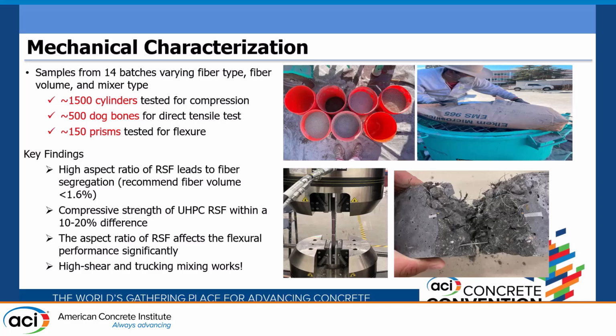So again, it's an optimization thing. If you use high aspect ratio, you're going to have a lot of fiber segregation issues, but you still want to have that flexural strength, so that's why you have to meet halfway. Also, we saw that a high shear mixer works for recycled fiber, but for truck mixing, you're going to see a video later on of what we observed on the truck mixing part.